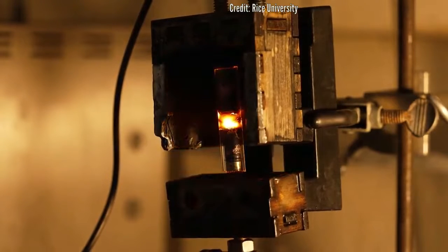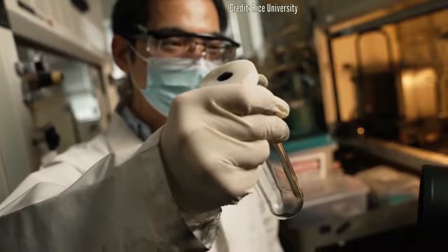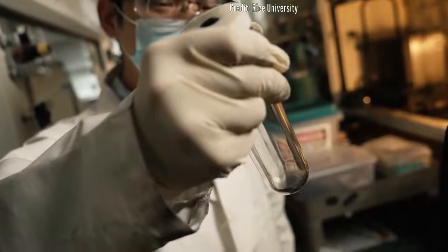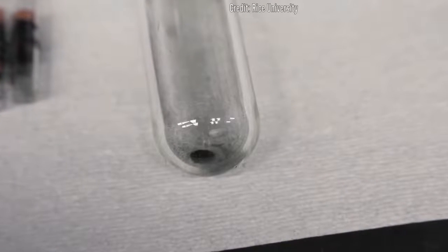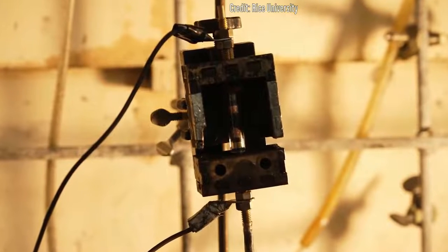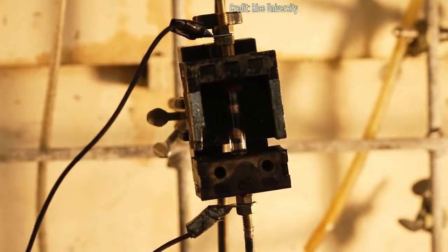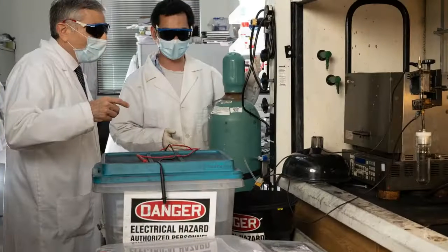The vapors are transported from the flash chamber under vacuum to another vessel, a cold trap, where they condense into their constituent metals. The reclaimed metal mixes in the trap can be further purified to individual metals by well-established refining methods. The researchers reported that one flash Joule reaction reduced the concentration of lead in the remaining char to below 0.05 parts per million, the level deemed safe for agricultural soils.